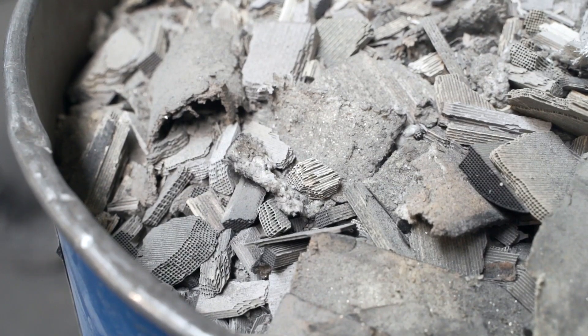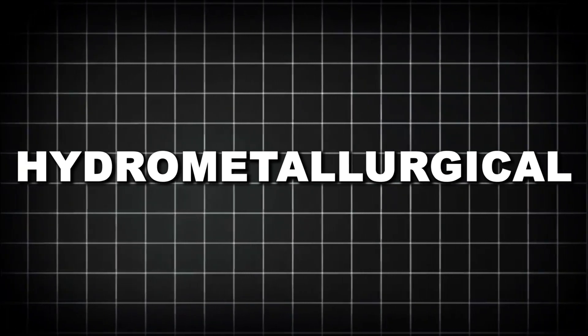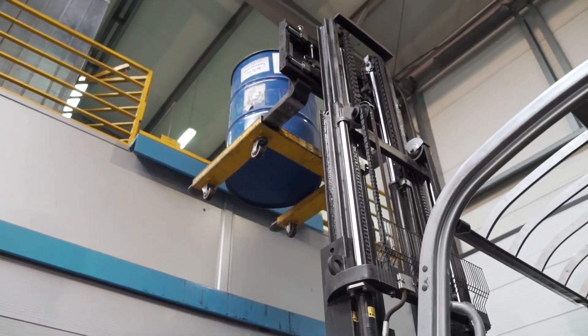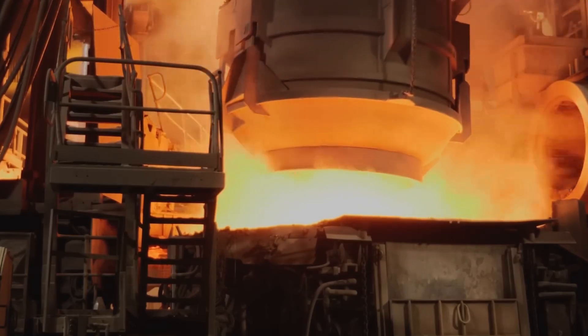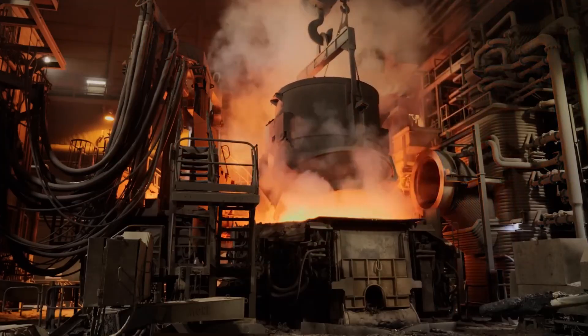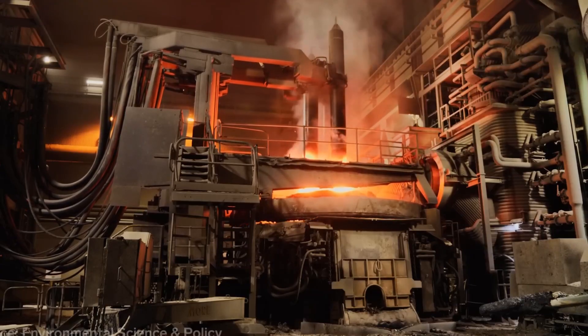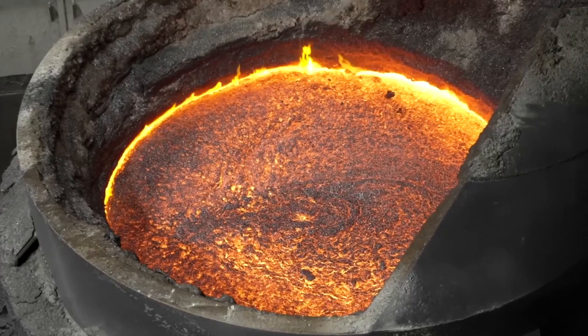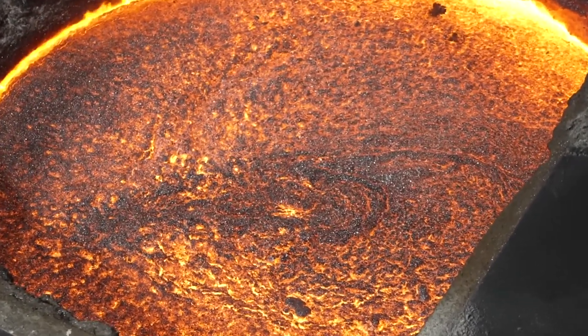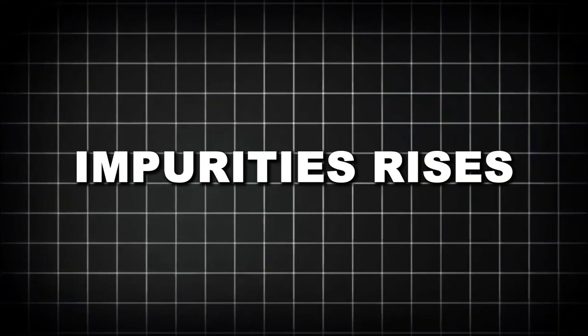There are two main ways to extract rhodium from the powdered material: pyrometallurgical and hydrometallurgical. Many modern refineries use a combination of both to maximize recovery. First comes smelting. In large induction or electric arc furnaces, the powder is heated to extremely high temperatures — well above 1,500 degrees Celsius. This melts the base metals, burns off unwanted compounds, and concentrates the PGMs into a dense metallic mat at the bottom of the furnace. Fluxes are added to help separate slag from metal. The slag — mostly leftover ceramics, oxides, and impurities — rises to the top and is skimmed away.